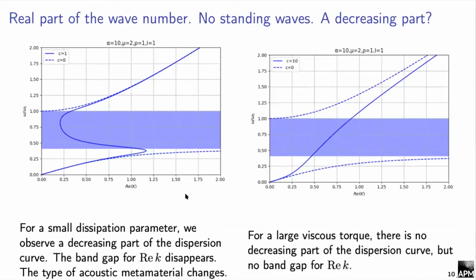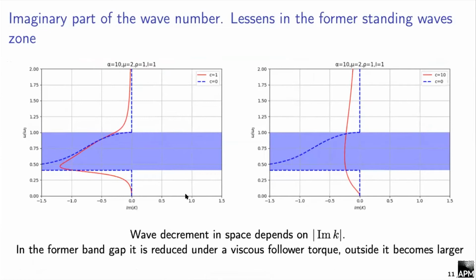The presence of the falling section suggests that due to the viscous tracking moment, we can change the type of our acoustic metamaterial. Note that for a large dissipation parameter, the section of the falling dispersion will disappear. What can we tell about the imaginary part of our wave number? Well, our wave rate will depend on the imaginary part. A numerical experiment shows that in the former band gap, a following viscous moment contributes to a slower wave attenuation.